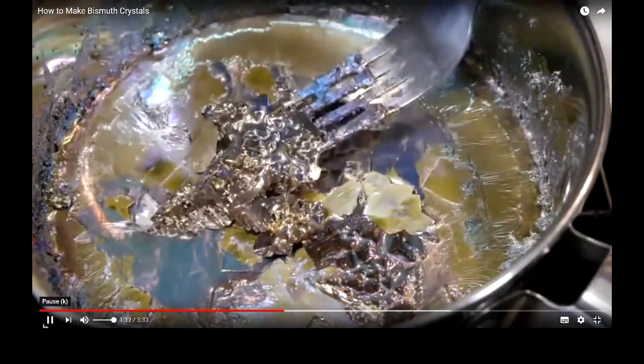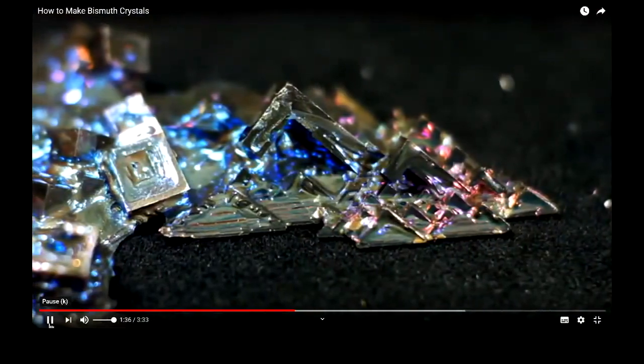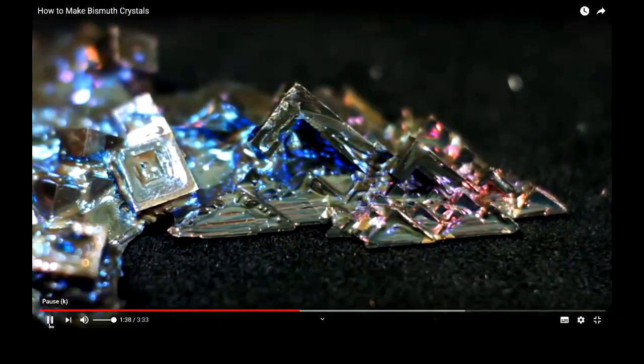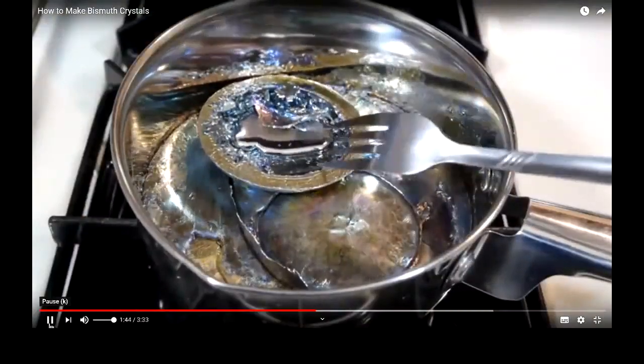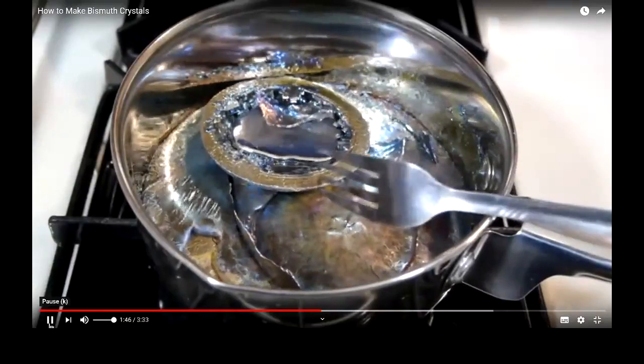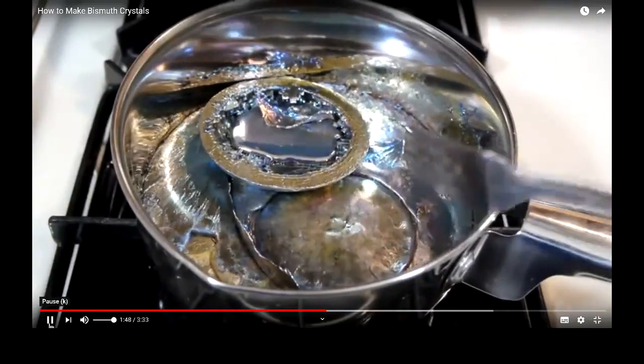At first, the crystals appear only silver, but a layer of oxidation quickly adds color, the shade of which is determined by what temperature the crystals are when they first contact the air. We only get one chance per cooling cycle to create crystals we're interested in, but if the results aren't satisfying, it only takes a few minutes to melt everything down and try again.